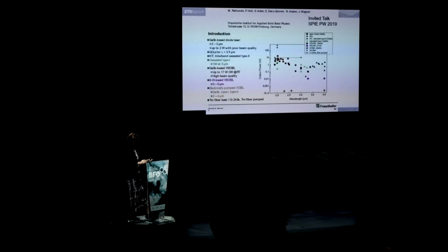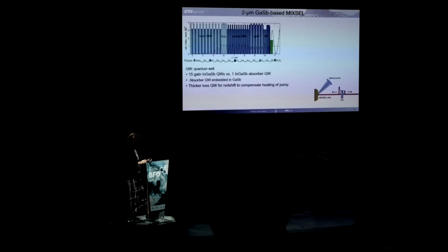Next slide. And when you look at the prior work before we started, there was actually some really nice work by the Fraunhofer group where they did CW operation of gallium antimonide-based VCSELs, optically pumped, and they could demonstrate up to 17 watt of CW output power at room temperature. And if you compare this technology to others like QCLs and so on, you see that the power performance of these lasers is very competitive and very attractive. But of course, the Fraunhofer group did not do the mode locking. So next slide. That was actually our job.